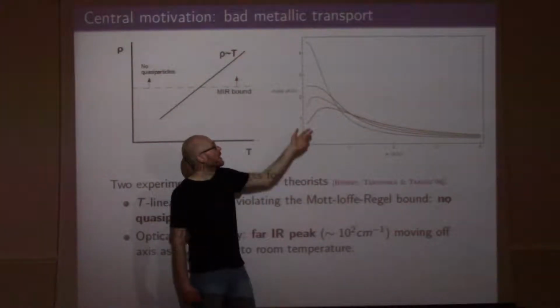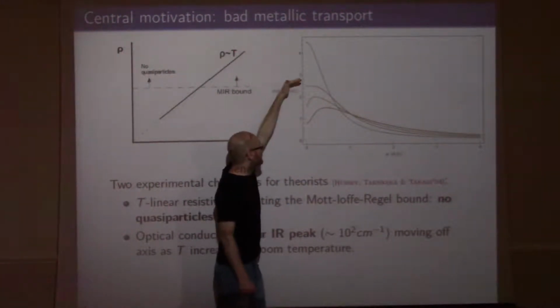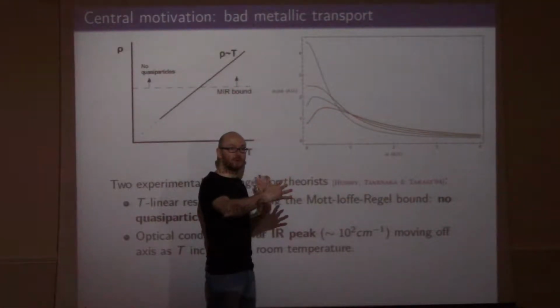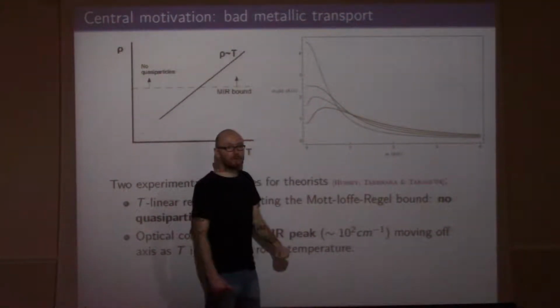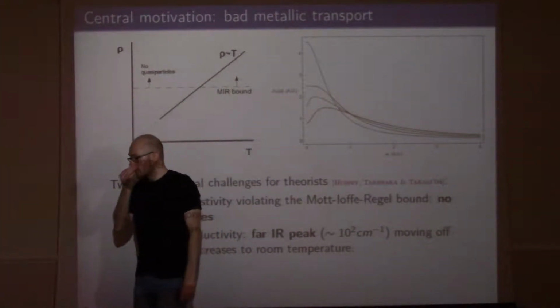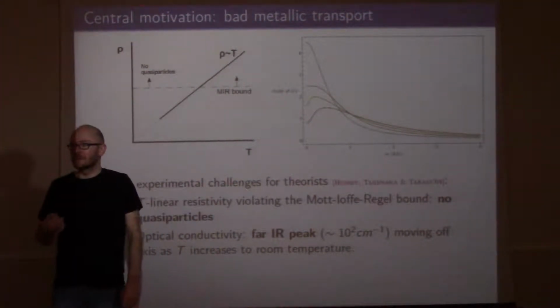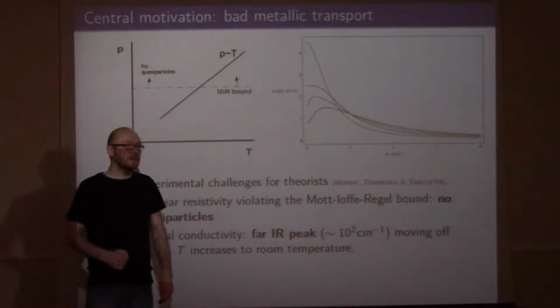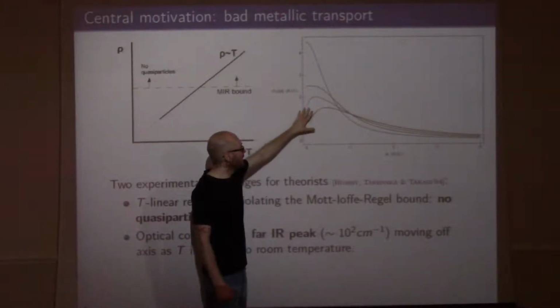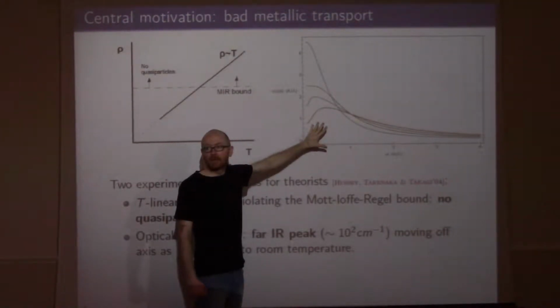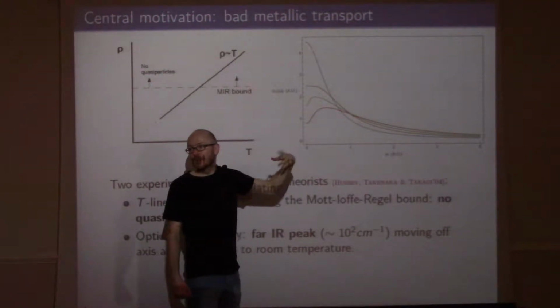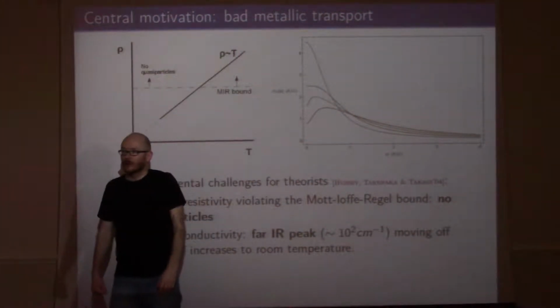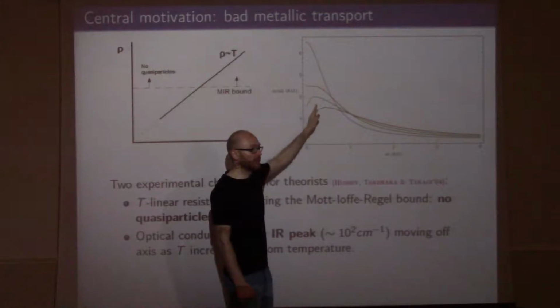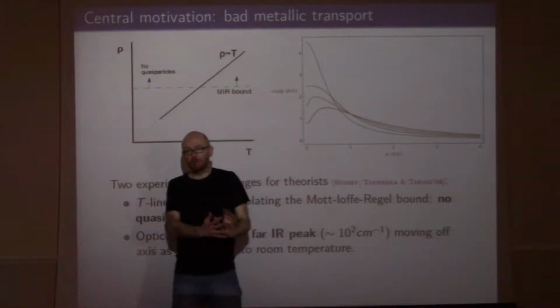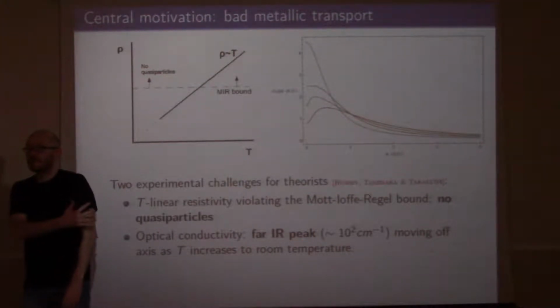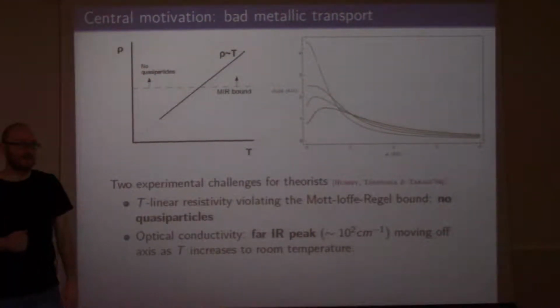Then even worse, when you increase the temperature, you see that the peak is getting squashed and broadens out. It eventually even moves off to non-zero frequencies. Now, you might be thinking that, all right, this is some UV resonance that's kicking in and giving me this peak. But actually, when you look at the frequency scales, these are extremely far infrared peaks. A UV resonance in these systems would be of order electron volts. These peaks, you measure them at maybe a few tens of milli electron volts. So they're really in the far infrared range, and they should really be part of the effective IR dynamics that describes these systems.